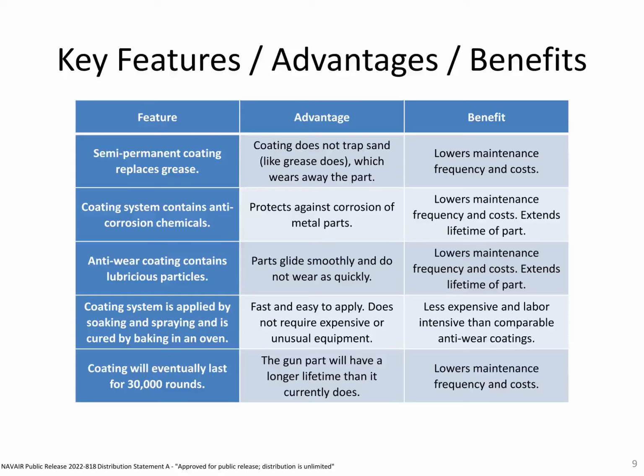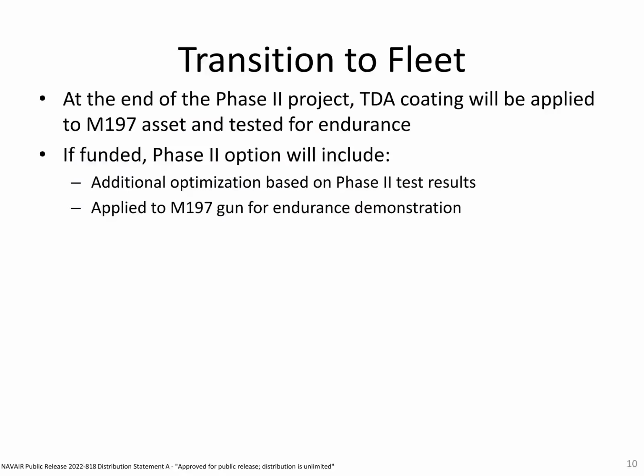Eventually, the coating will last for 30,000 rounds, so this will extend the lifetime of the gun beyond what it currently has, which again will lower maintenance frequency and cost. The plan to transition this technology to the fleet is to do several runs initially of optimization, applying the coating to the M197 gun and running a series of endurance tests. If funded in the phase 2 option, we will do additional optimization of the coating based on the phase 2 test results and continue to test this coating on an assembled gun for an endurance demonstration.